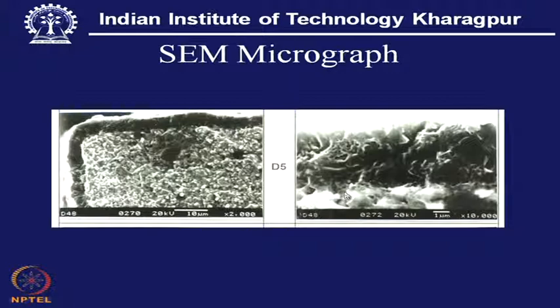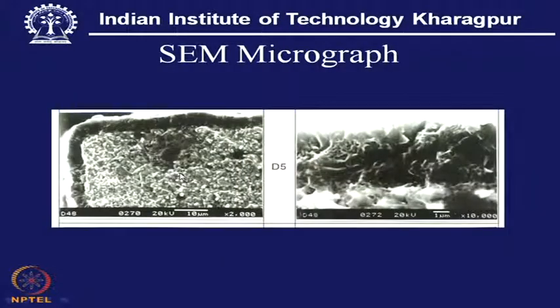So, after seeding, if we take a picture, it is even possible to see the pores or voids formed because of cobalt etching, and find whether these diamond seeds are really captured in those pores and voids, because from there the tree will grow, spread its branches and cover the whole area, and we have a deep anchorage inside the cavity. So, all those things can be given by this SEM picture.